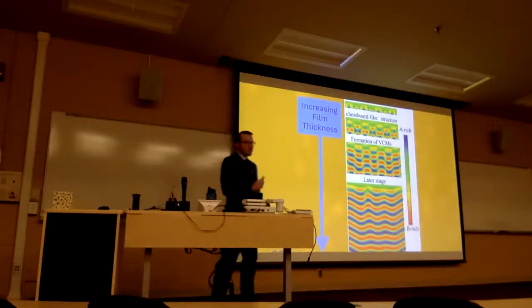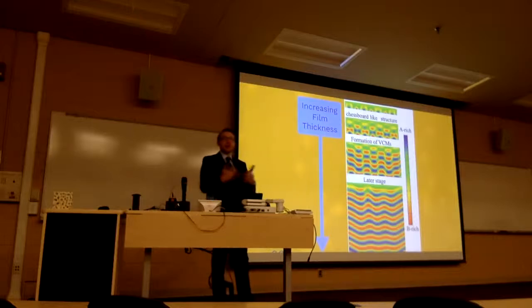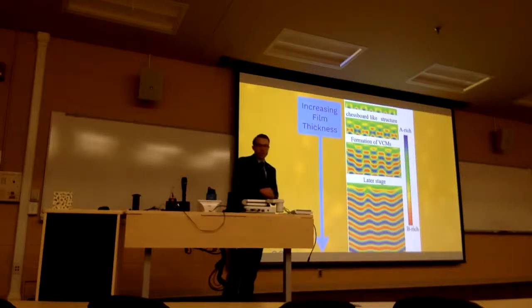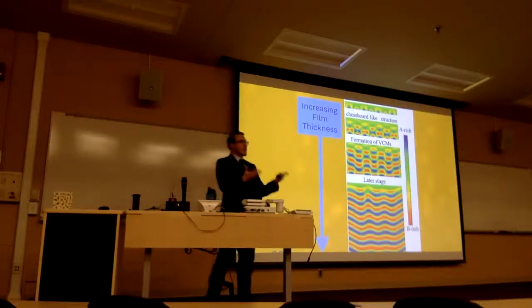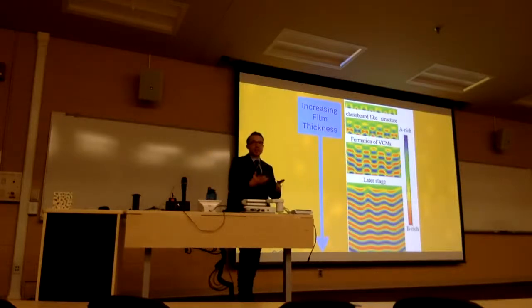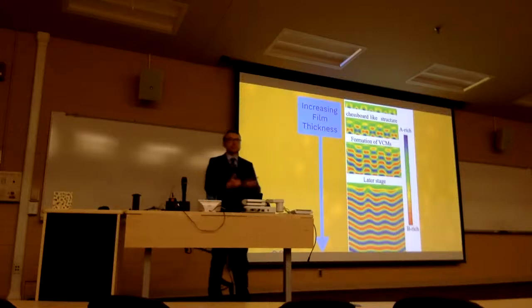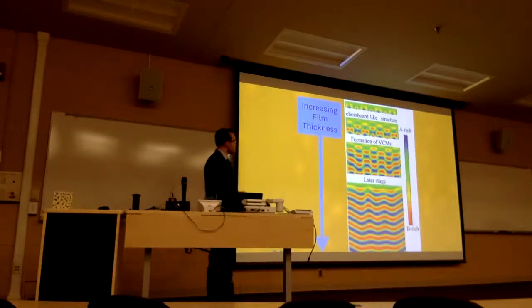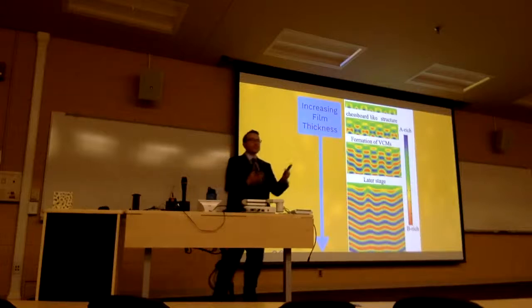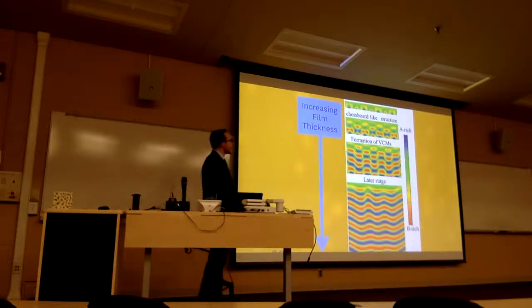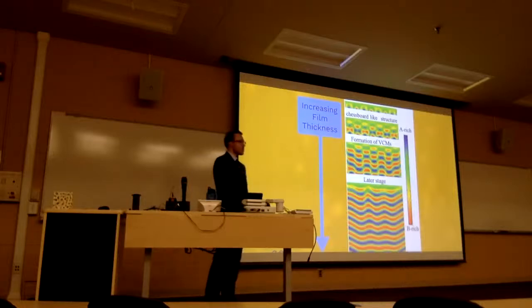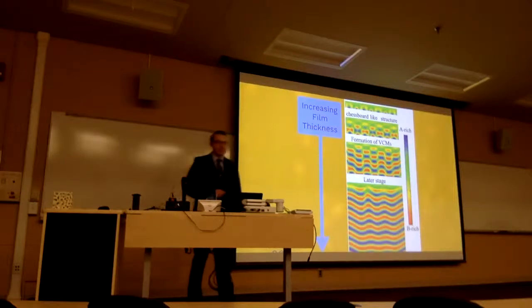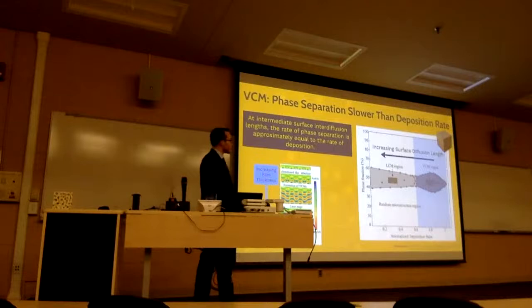And in the first few layers of deposition, the system tries to phase separate into these red and blue rich regions. Unfortunately, by the time the next layer arrives on the substrate, that underlying layer hasn't reached terminal composition or fully demixed on the substrate. And so that first layer starts stealing like atoms from that second layer, forming a chessboard or checkerboard-like structure. Surface energy arguments actually start to then interconnect those phase-separated domains, and you can see that at later stages in deposition, we have a VCM-like morphology at lower diffusion length.